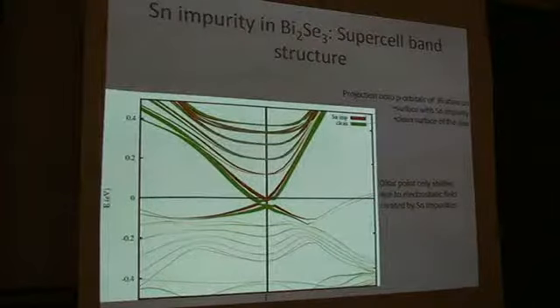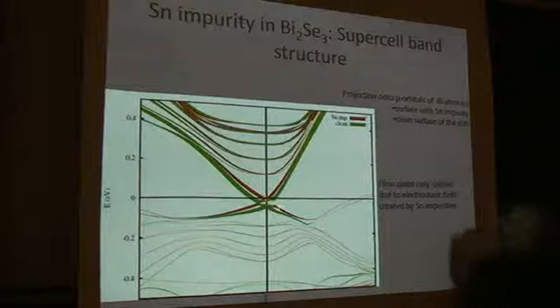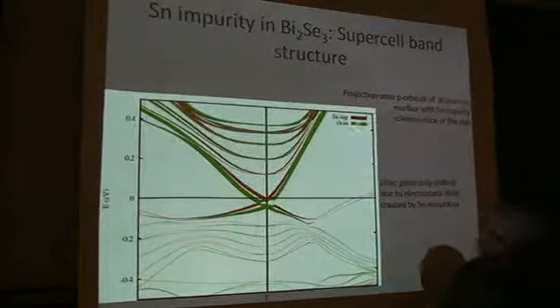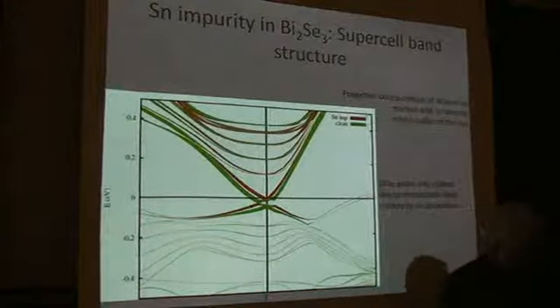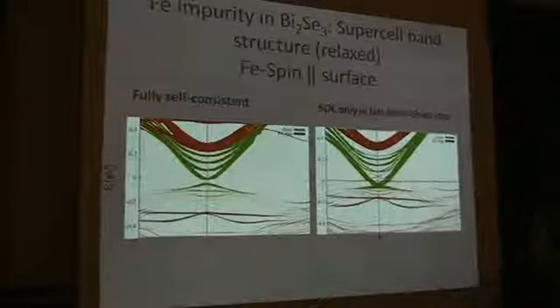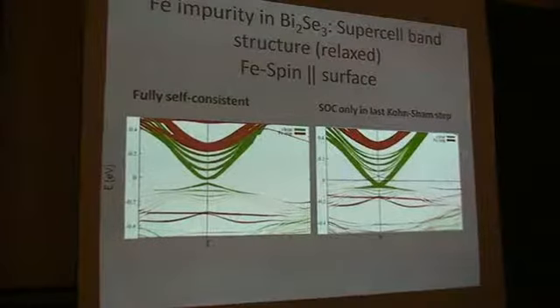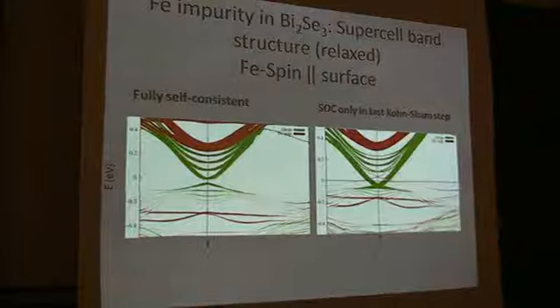Now, if I look at the tin impurity, then I can measure the band structure on the top layer and plot a projected band structure for the sites where I have a tin, and look at the bottom where I have a clean surface, and we will see that there is very little change. Now, in a way, it means I don't know exactly whether there will be this impurity resonance for the tin. So I don't know what comes out from this one. But for iron impurity, there is already something very interesting, at least in the calculation we've done.